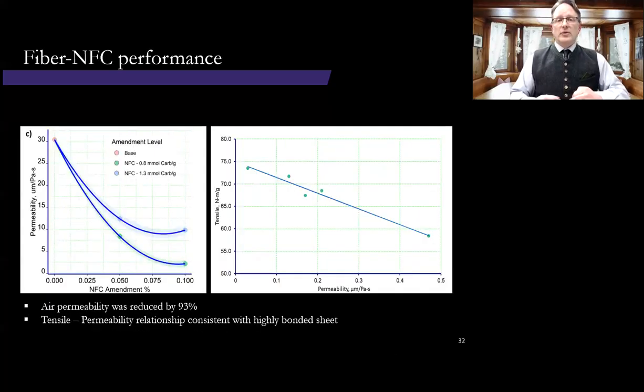With regards to permeability, I'll say one thing about air permeability: it's a test that's really affected by sheet densification and blocking of the pores by nanofibers. And so what we observed here, again, as with a lower charge fiber and amendment increase, we got a 93% reduction in permeability versus the base sheet, not nearly as strong a reduction with the higher charge. If we look on the right here and compare tensile development with permeability, as we reduce the permeability, we see an increase in tensile. And this confirms that our bonded area was increasing due to the nanofibers present.